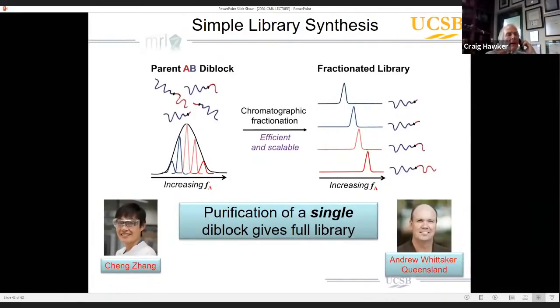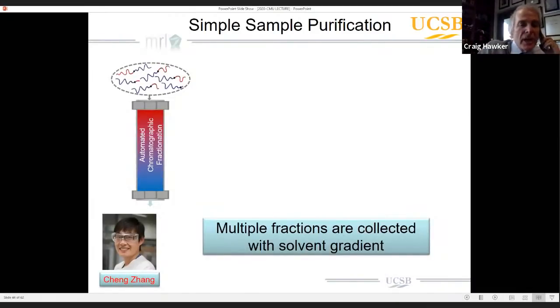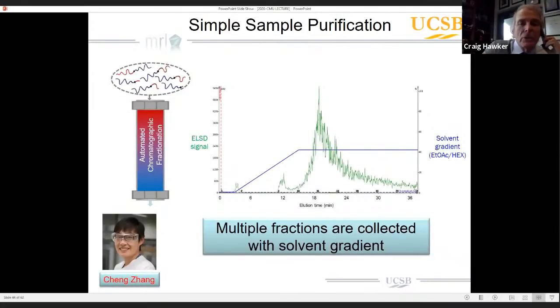But if you just remember, again, we see the trap. The trap is that we had to do multiple polymerizations to make this library and then examine the library. And again, you see where this concept of user-friendly chemistry comes in handy. This is a collaboration with Andrew Whittaker from the University of Queensland in Australia and a joint postdoc, Cheng Zhang, who took the concept of controlled polymerization, married it with automated chromatographic separation, and takes an AB diblock, one parent sample, and then makes a fractionated library. The hope is that the fractionated library would scan all of the fraction volumes that we could then look at for morphology. This is in essence what Cheng did using a simple gradient solvent elution profile.